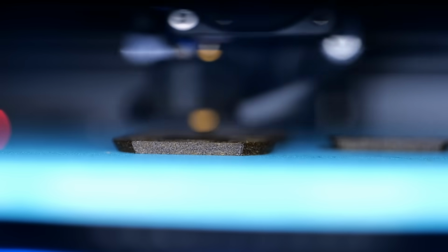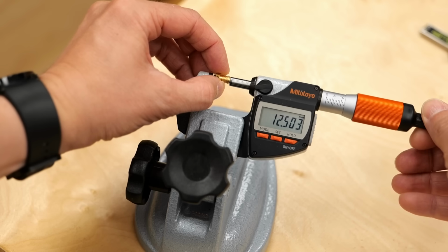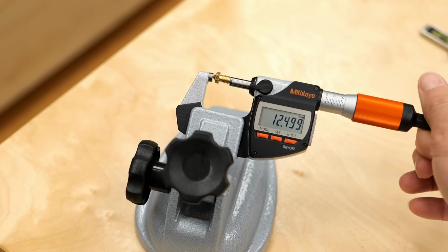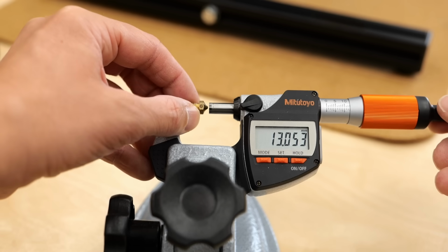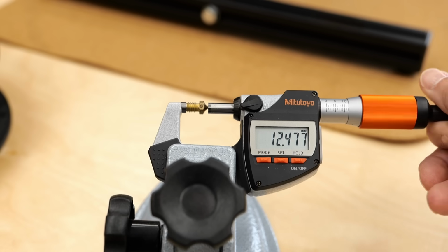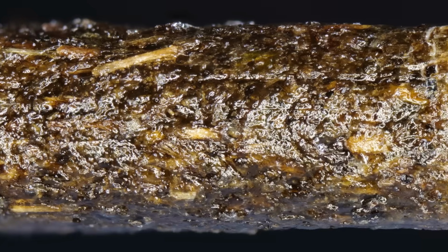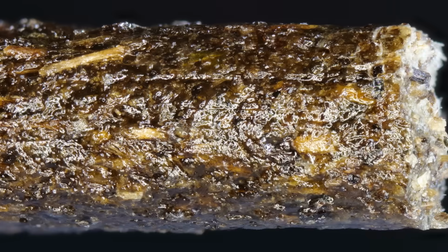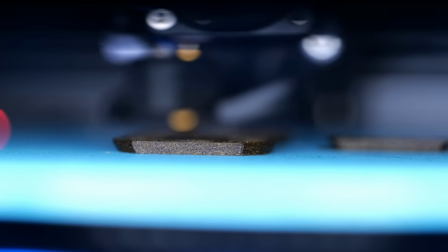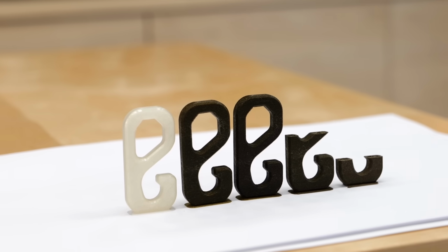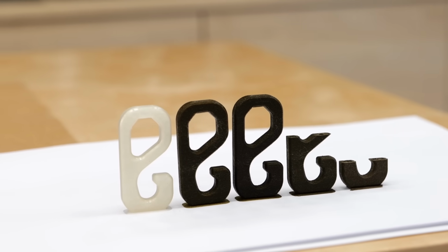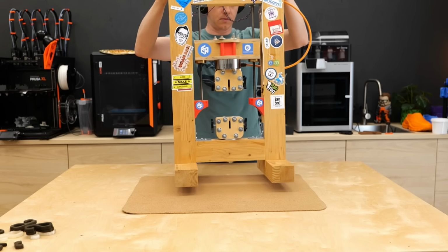If you're, by the way, wondering whether such a fiber material can damage your nozzle, I printed about 100 grams of PLA through our CNC Kitchen unleaded brass nozzles, and it lost 50th of a millimeter in length. That's not a lot, but after such a small amount of material, it does suggest that cow dung fibers can potentially damage your nozzles if they're not made from hardened steel. But back to the strength tests. I still went ahead and tested the parts that printed on my DIY tensile tester.